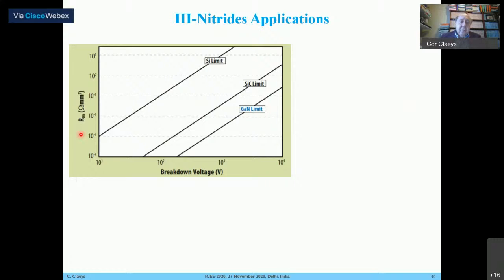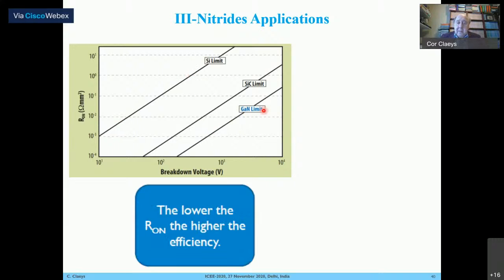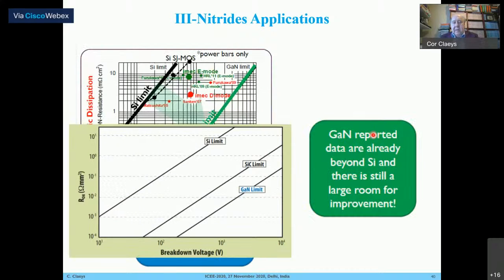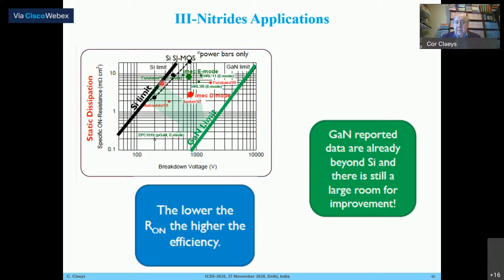And if you look at the on-resistivity versus the breakdown voltage, there is a limit for silicon, there's a limit for gallium nitride, and there's a limit for silicon carbide. And the limit for gallium nitride is further away than for silicon carbide. And I know there is a strong debate going on between silicon carbide and gallium nitride, which of the two is the most promising material for future devices. Well, I would say depending on the final application, there is a market for each of them. However, today, the data reported for gallium nitride, as you can see, is very, very promising and is reaching further than the silicon limit, but not yet the limit for gallium nitride. So that means, notwithstanding the excellent data, there is still room for improvement.